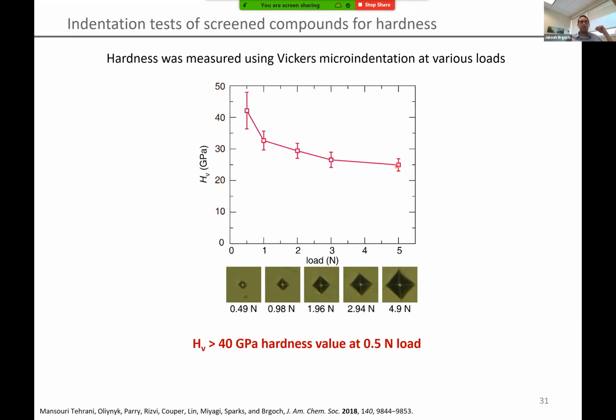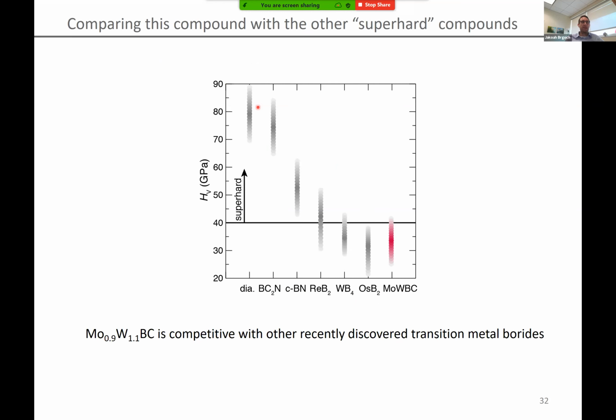It bottoms out around 26 gigapascals, so this is still quite good. We were really happy with the fact that this is sitting around 40 gigapascals, at least at a half a Newton. So where does this compare with respect to these other compounds?